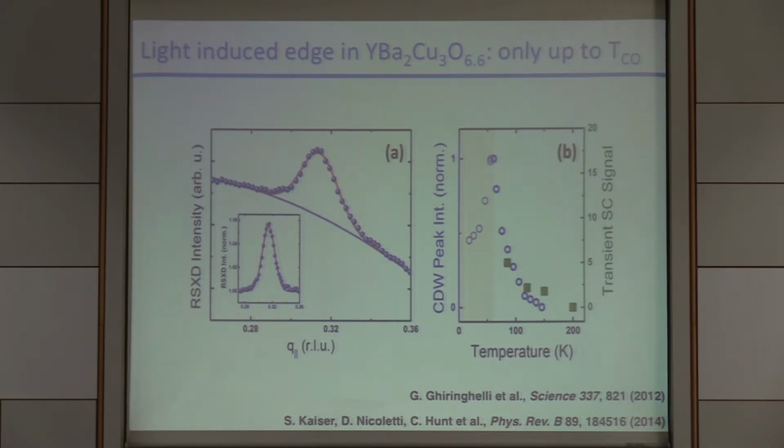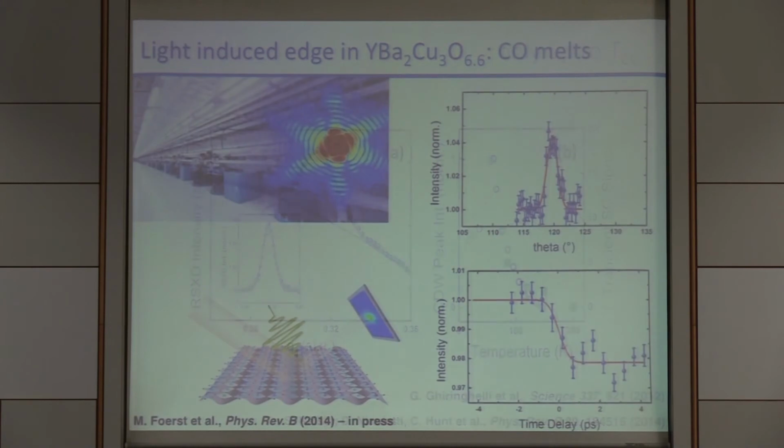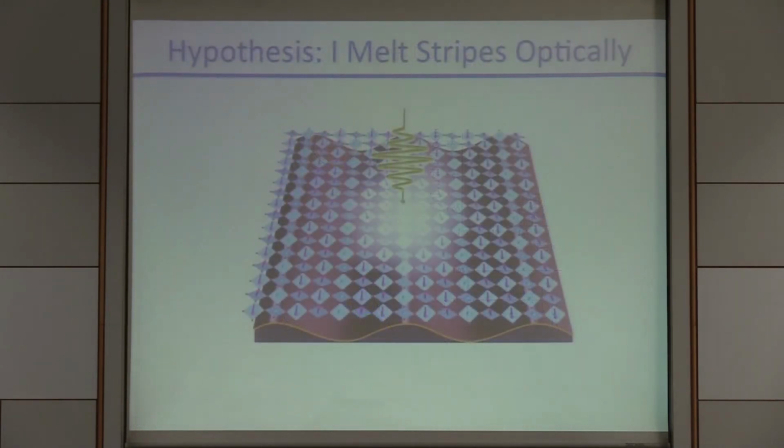So 1/8 again is something that confirms this. These are again LCLS data that show that we do the same experiments, and we show that this particular peak melts in conjunction with the appearance of this plasma edge. So the hypothesis at 1/8 doping still stands.